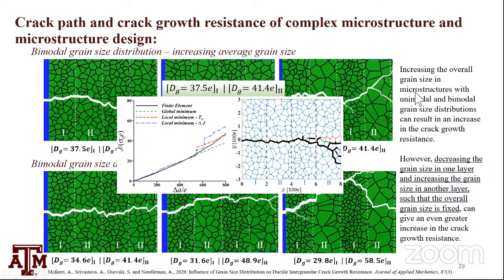We also came up with the obvious answer: if you increase the grain size, toughness increases. We've known that for 50 years. But we also came up with the non-obvious answer that decreasing the grain size in one layer and increasing it in the other layer, so that the average grain size stays fixed, has a greater effect than just increasing the grain size as a whole. This second part is important because sometimes we need strengthening from the finer grain, and we can then get toughening from the larger grain.